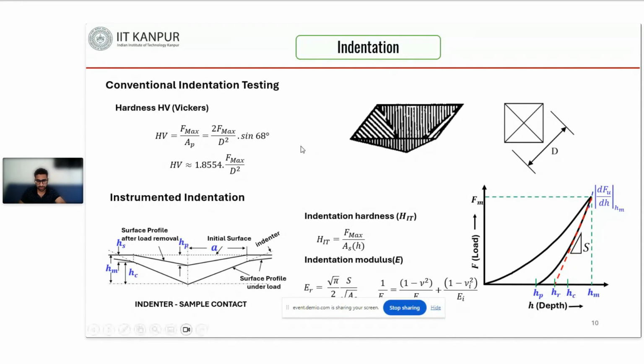So we jump to instrumental indentation, which was developed with the Oliver-Pharr method. Here is how instrumental indentation testing works. An indenter of a known geometry is pressed against a flat sample, and during the complete indentation testing, the load and the indentation depth are continuously monitored. During the loading part, we get a loading curve, a holding curve, and then an unloading curve.